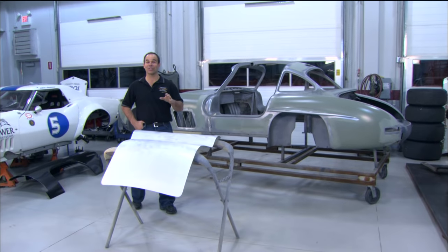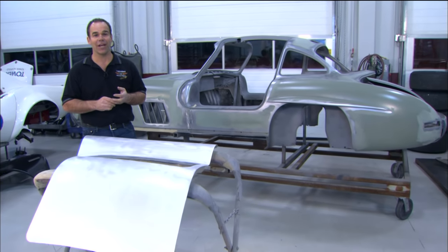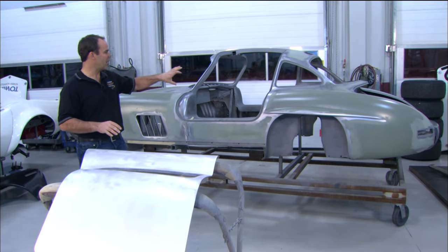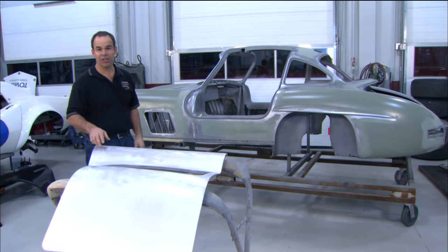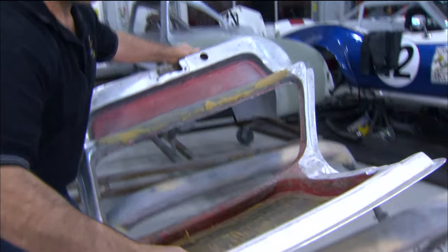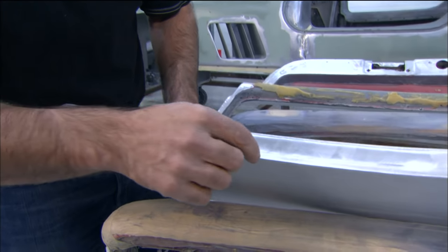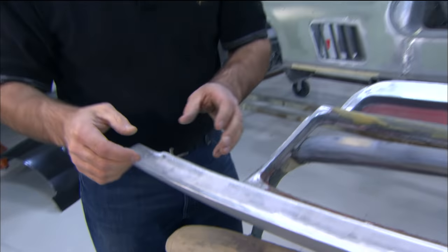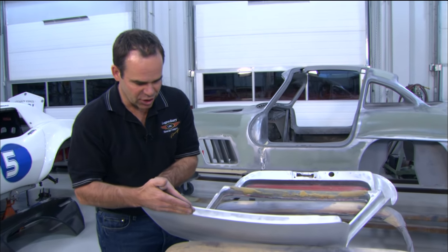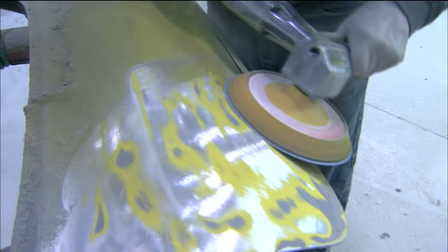There are a few things in life that are sometimes just better if you do them by hand, and one of those things is stripping an expensive car. You can use soda, you can use sand, you can use walnut shells, but if you ruin one of these panels, you can't just phone up one of those repop panel companies and order one up. So what we did is we stripped the entire exterior skin by hand. You've got mild steel and aluminum, and the process a lot of these panels are put together with is spot welding — two sheets of aluminum spot-welded together. If you were to use baking soda and it got in between those two sheets, it absorbs moisture and is just going to puff them apart. With aluminum panels you're just better off to do it by hand.